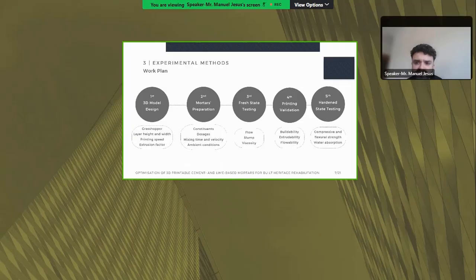So moving on to the experimental plan, it began with the computational modeling of the test specimen in Grasshopper. During this stage, we designed the 3D model, choosing the layer dimensions, the printing speed, the extrusion factors, and later on the G-code was created. Then the second stage focused on mortar preparation, and this involved the characterization of the constituents, the determination of the dosages, the mixing times, and the speed. Also, environmental conditions like air temperature and relative humidity were strictly controlled throughout this phase.